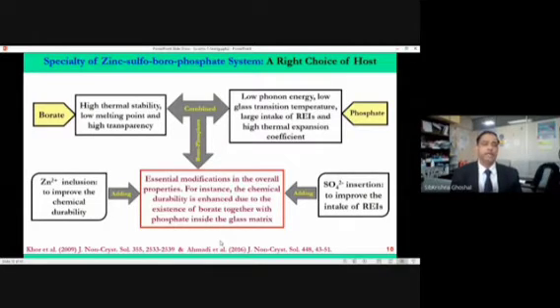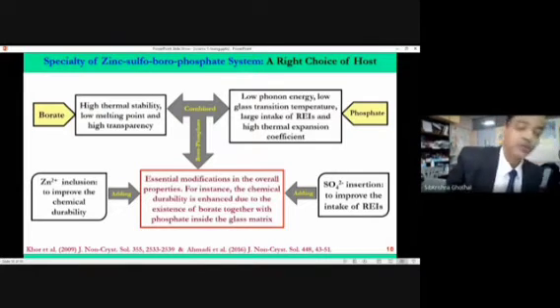Borate has high thermal stability, low melting point, and high transparency. That's why we choose borate. Phosphate we choose because it has low phonon energy, low glass transition temperature, and large intake of rare earth. It can take a lot of rare earth concentrations. Zinc we use to chemically stabilize the network or the glass ceramic structure, and sulfate we use basically to improve the intake of rare earth. So this is already a nice kitchen chemistry. We cook up all this material to get a good functional material.